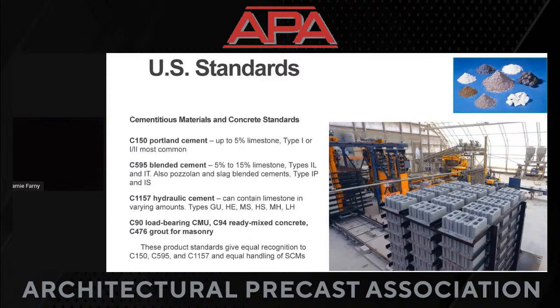The 1T means it has 3 components. So the 2 other components are something that isn't clinker. It can be a combination of pozzolan, slag, limestone. It can be 2 of pozzolans and slags with a limestone. So we are just introducing the idea that type 1L is the most common PLC, or Portland limestone cement, that you will see on the market right now. But many of our members may be investigating these type 1T cements also going forward, where they have something in addition to clinker and limestone in them. You can specify a PLC as a 1T. So that's probably coming in the future because we're still trying to reduce the footprint.